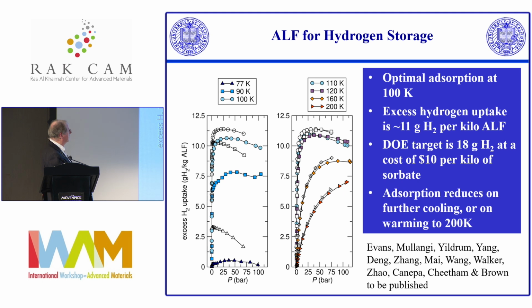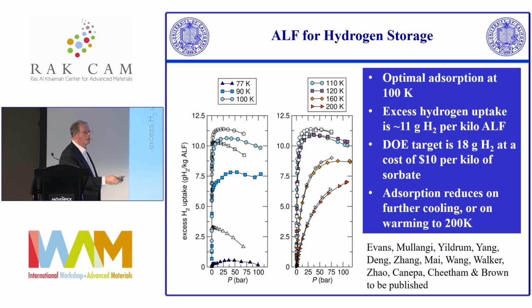The other thing we've been looking at, and this is kind of hot off the press, is hydrogen storage in ALF, and it adsorbs hydrogen extremely well, optimally at about 100 degrees Kelvin, which is not a bad temperature to be at. We get excess hydrogen uptake of about 10 to 11 grams of hydrogen per kilo of ALF. There are DOE targets, and an article with Jeff Long and some of his collaborators on this in Nature Energy. Their target is 18 grams of hydrogen per kilo of molecular sieve at a cost of $10 a kilo for the sorbent. Of course, we know what the materials cost is.